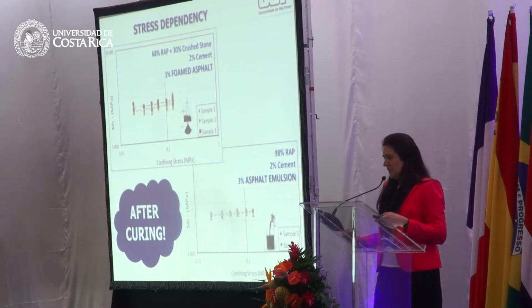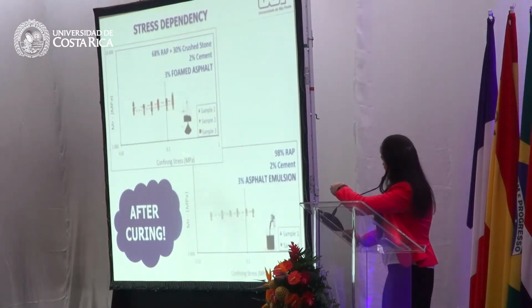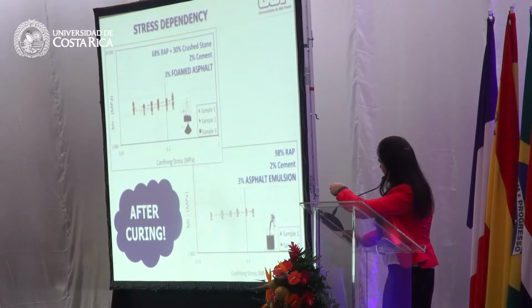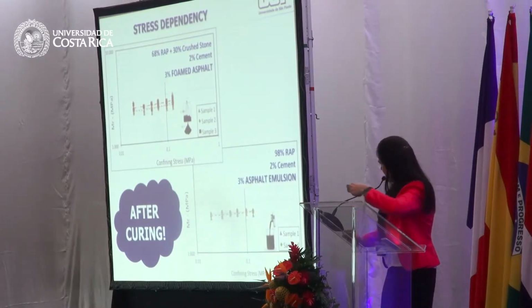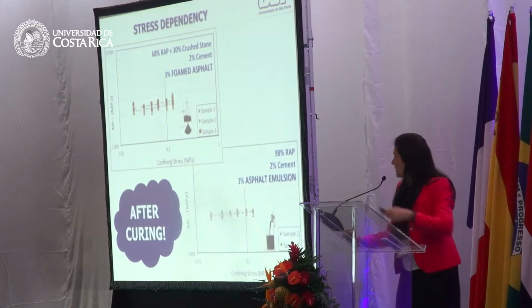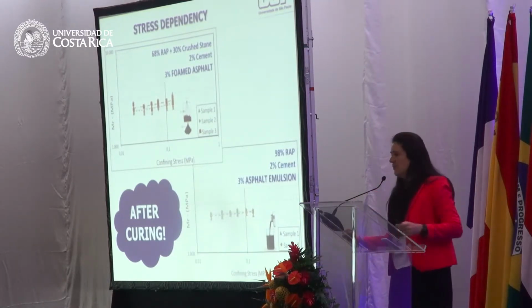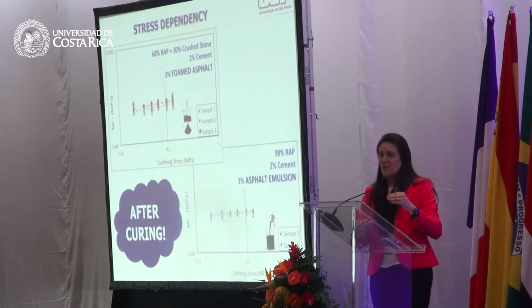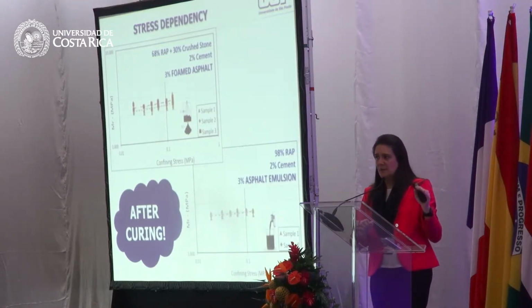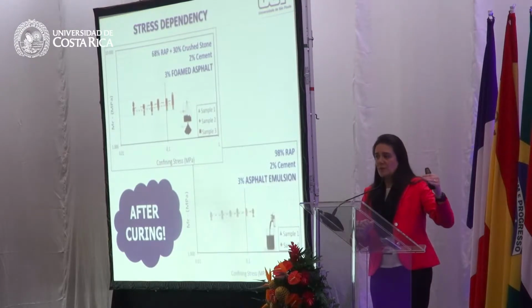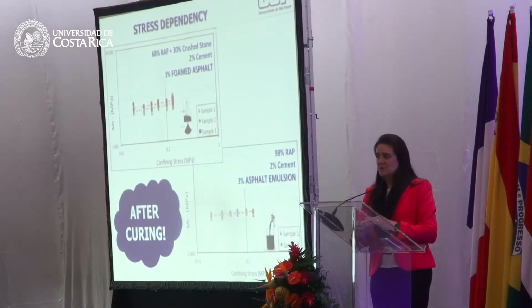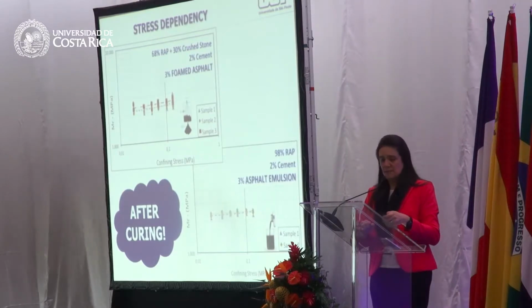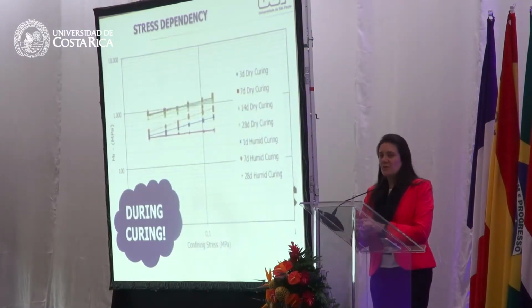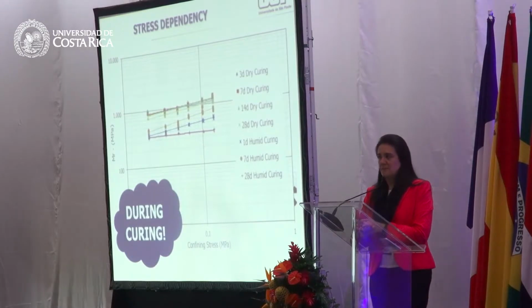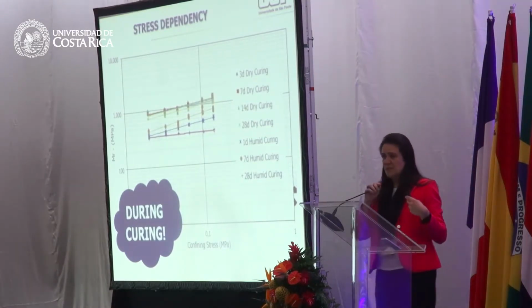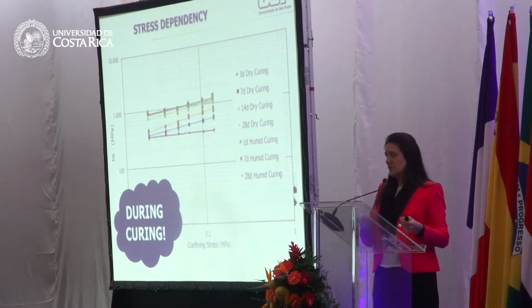These plots, if you look, the first one is for foamed asphalt mixture, and this one is from asphalt emulsion mixture. Here are the compositions of both of them. If you wait for the curing process, and we'll talk about that a little bit more, most probably these mixtures will not be so stress dependent. But during the curing process, they are. We know that already from our results, from other researchers' results too.